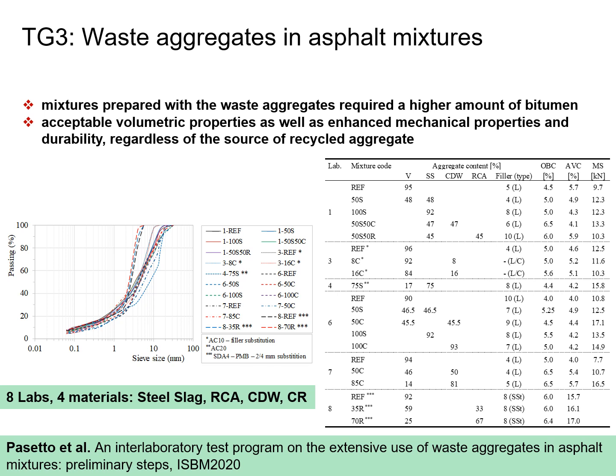TG3 involved waste aggregates in asphalt mixtures. In this case, we had 8 labs that participated using 4 materials. The materials were steel slag, recycled concrete aggregates, construction and demolition waste, and crumb rubber. We see here in this table some of the results. In most cases, the mixtures that were prepared with waste materials had a higher binder content. So you see the optimum binder content is listed here. We were able to reach the volumetric properties that were required, and also the mechanical properties were completely acceptable, as you see in the Marshall strength in this table.